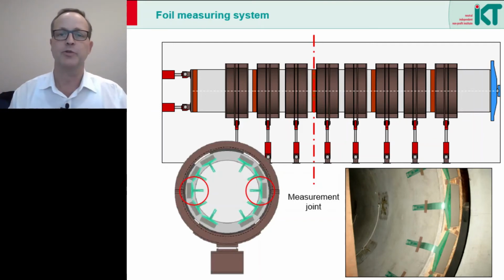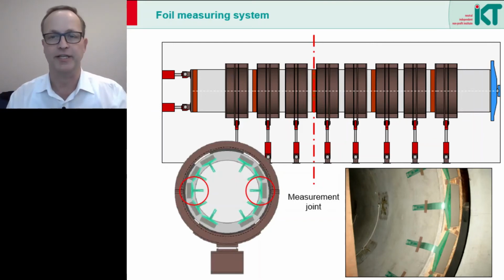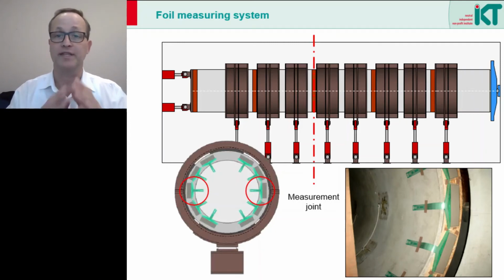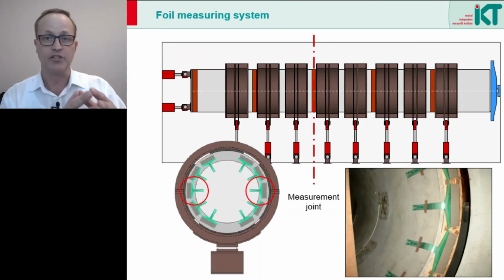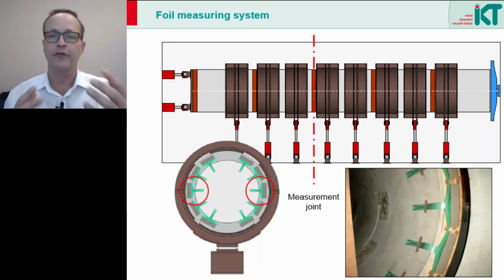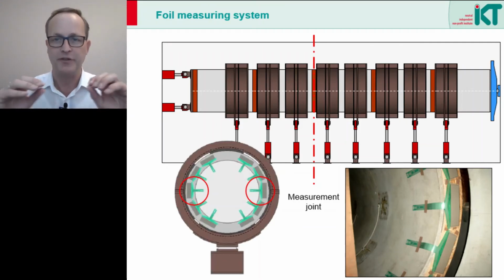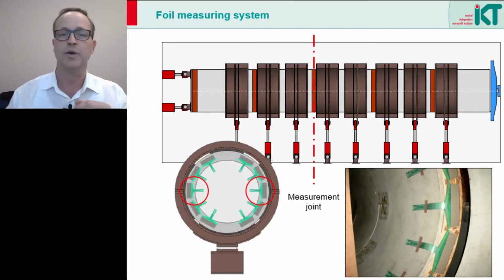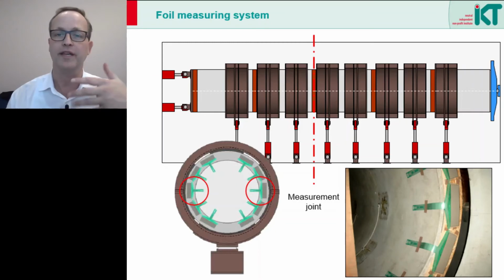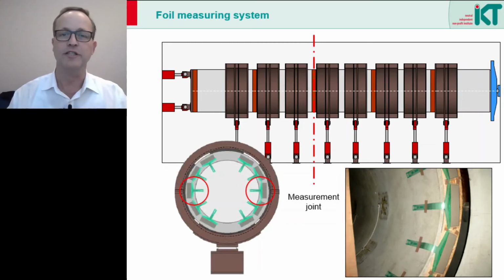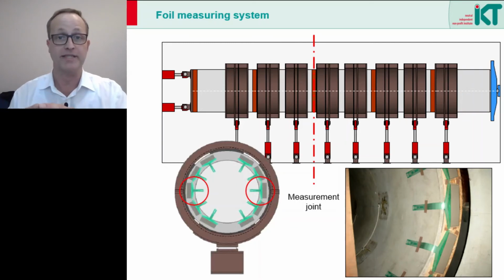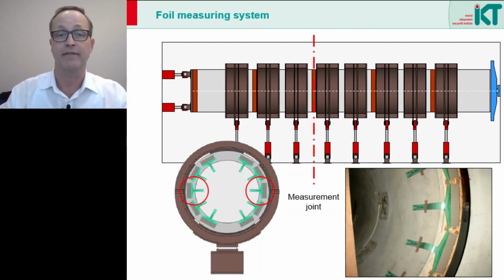For this purpose, we used the foiled sensor measuring system in the pipe joint between the second and third pipe. The picture shows the cross-section of the measurement joint. The foiled sensors are mounted in the spring line of the pipe and above and below it. The stresses were then measured continuously over the entire simulated jacking process. Let's now take a closer look at the results for the foil measurements in the left and in the right extreme of the spring line.